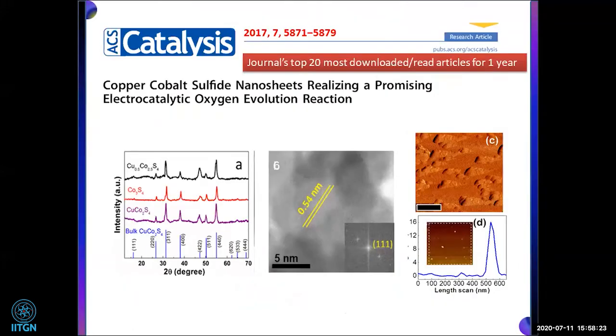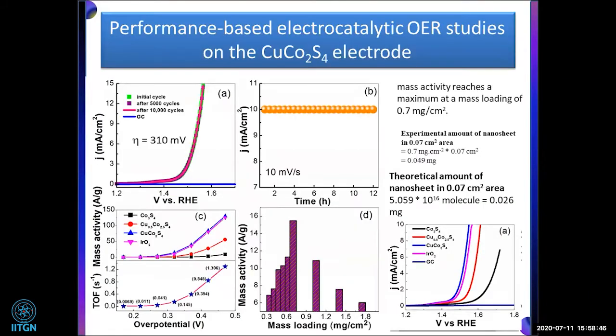So after that, we started our journey for water splitting. This is the copper cobalt sulfide nanosheets, as Dr. Sudhanshu mentioned. We prepared it by a very simple hydrothermal technique. These nanosheets are 12 nanometer in thickness, which is determined from the AFM. And without going too much into the characterization, I'm going to the electrocatalysis part here.